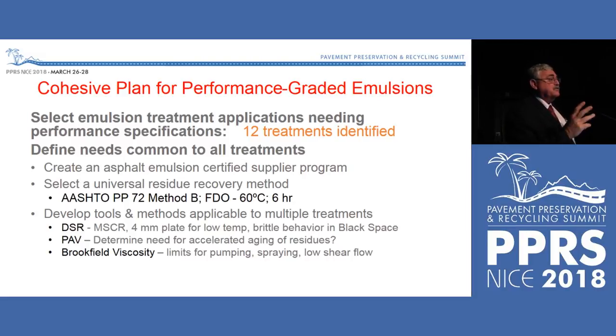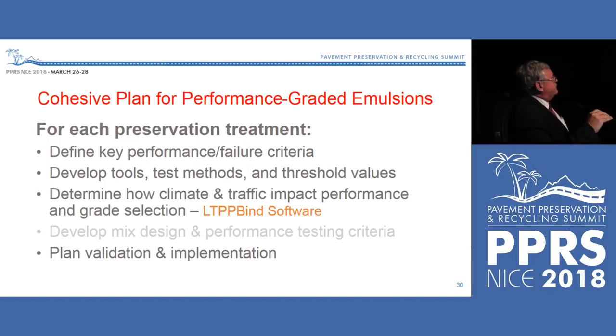We're not sure, so we're testing materials with and without aging to try to understand whether aggregate loss over the long term is due to asphalt aging for chip seals, for example. And finally, Brookfield viscosity: we're using the multi-shear rates that my esteemed colleague Bernard discussed earlier to try to understand different things. Thank you. This plan then has to look at each individual application and understand what the performance